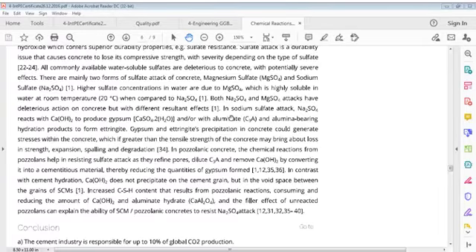There are mainly two forms of sulfate attack of concrete: magnesium sulfate, MgSO4, and sodium sulfate, Na2SO4. Higher sulfate concentrations in water are due to MgSO4, magnesium sulfate, which is highly soluble in water at room temperature, 20 degrees Celsius, when compared to Na2SO4. Both Na2SO4 and MgSO4 attacks have deleterious actions on concrete, but with different resultant effects.